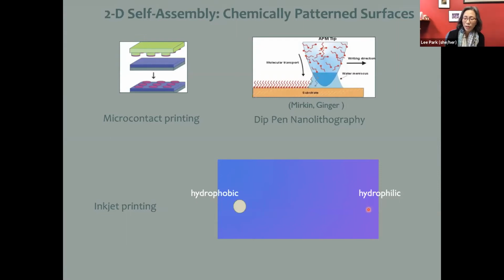Now if you imagine putting a drop of water onto this surface, the left edge of this water drop is experiencing a relatively hydrophobic environment, and it's going to try to retract from that environment. But the right edge of this water drop is going to be experiencing a more hydrophilic environment, and it's going to try to spread out, try to wet that side. As a result, this water drop is in fact going to move across the surface. So you can get this water drop to walk across the surface based on the chemical patterning of the surface. You can do various things with this. You can get water to walk uphill by just tilting your paper up at an angle.